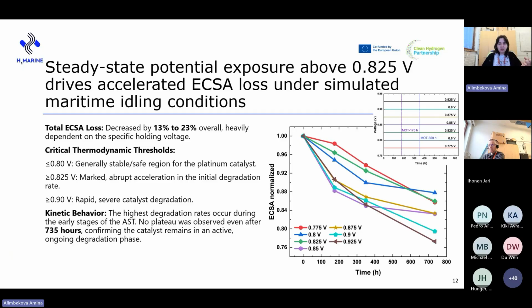If we look at the early stages of the accelerated stress test, basically beginning of test to the middle of test, we will notice that the degradation rate increases significantly once the holding voltages are above 825 millivolts, so they divide into those 2 groups. This gives us a first hint that exposing the cathode potentials to elevated voltages is the primary voltage-driven catalyst degradation during the ship idling phase.